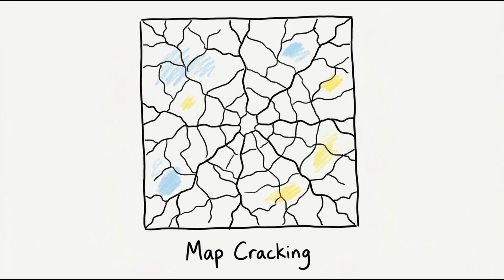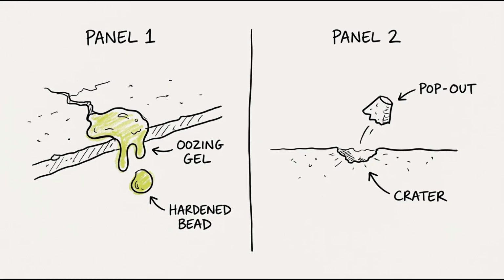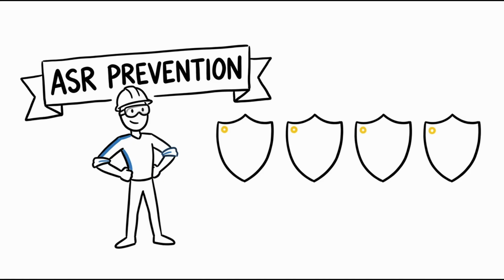The most telltale sign is map cracking, a spiderweb pattern of fine, interconnected cracks spreading across the surface, because the swelling is happening more or less randomly throughout the entire slab at once, not from a single external stress point. Sometimes you'll also see gel actually oozing out through the cracks and hardening on the surface, or small cone-shaped chunks of surface popping out entirely, called pop-outs, where a reactive particle right near the surface expanded and blew its lid. So if this reaction is baked into the chemistry of the ingredients themselves, how do engineers stop concrete from quietly destroying itself for the next 30 years?